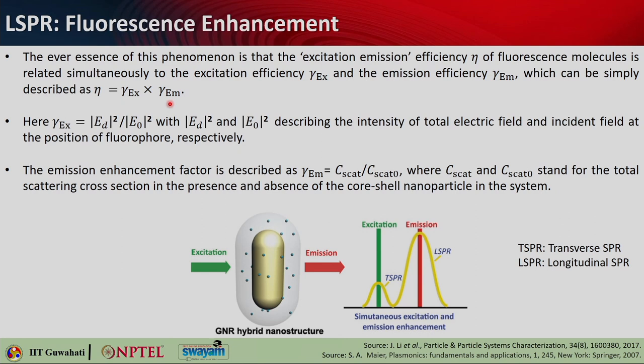In one gold nanorod example, the transverse LSPR was matched to the excitation wavelength and the longitudinal LSPR was matched to the emission wavelength. This dual matching dramatically boosted both excitation efficiency and emission efficiency simultaneously — a double impact. Previously, researchers used a single LSPR tuned to either excitation or emission, or a compromise wavelength in between. The nanorod approach with unpolarized light excites both transverse and longitudinal plasmons together, boosting both efficiencies.